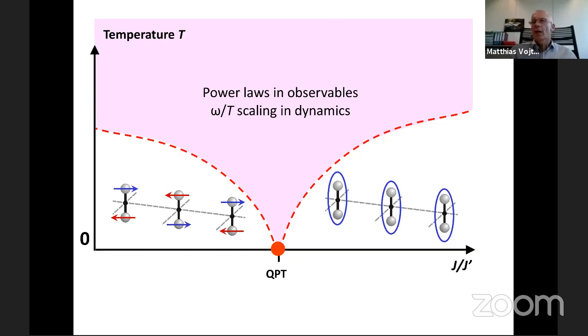Of course, it's clear if you go to larger and larger spin, then finding spin liquids will become increasingly improbable because large spins behave classically and like to order. Which means if you want to look for spin liquids, you should better do this for small spin. The Kitaev model nicely shows that in the general phase diagram, the regime of a spin liquid is relatively large for s equals 1/2, then it shrinks if you go to s equals 1, and whether it continues to exist for s equals 3/2 is not known at this point. So spin liquids exist for higher spin, but that is not a good place to search simply because the spin liquid phases get narrow.